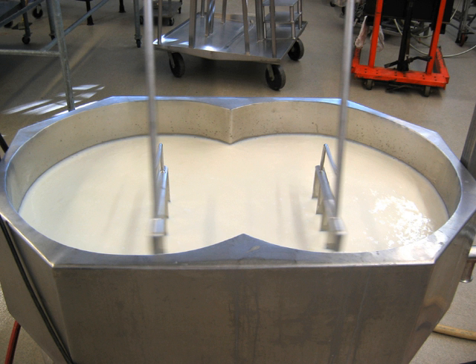Cronobacter sakazakii greater than 6.7 at 67.5 degrees Celsius (153.5 degrees Fahrenheit). Listeria monocytogenes greater than 6.9 at 65.5 degrees Celsius (149.9 degrees Fahrenheit). Salmonella enterica serovar Typhimurium greater than 6.9 at 61.5 degrees Celsius (142.7 degrees Fahrenheit).